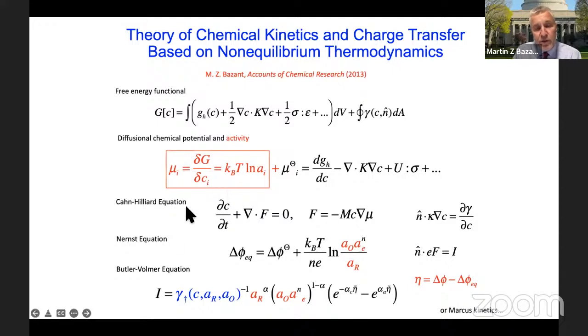Transport leads to the so-called Cahn-Hilliard equation, where simply the fluxes are driven by gradients of chemical potential. That's very standard. In fact, it's named after Cahn and Hilliard for their seminal work on binary metal alloys in the 1950s, but in fact, the same equation was written down and studied by van der Waals in the late 1800s, and then essentially forgotten until Cahn and Hilliard, and also Ginzburg and Landau in physics,